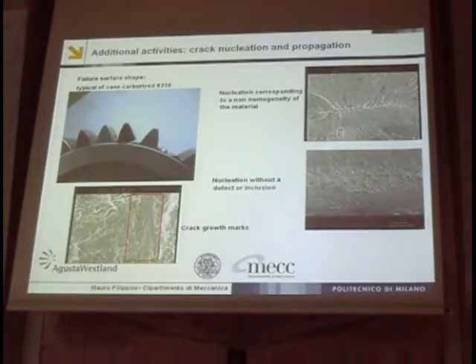A second observation was an extensive examination of the failures. Just in one case, over all the tests we performed, we got a failure starting from a metallurgical defect. This is a concentration of chromium, which is typical also in bearing steels. You can find those features also in bearing steel. In all the other cases, we found either fractures starting from the surface, or it was really impossible to determine which was the failure initiation site.